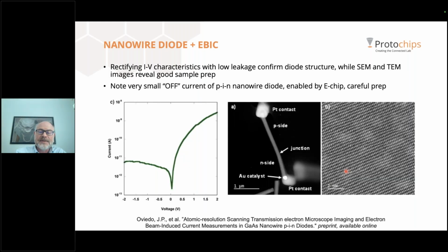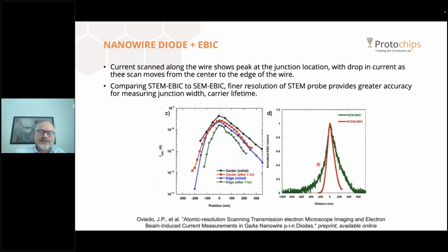So the first thing you want to do is measure the diode and confirm that it has diode behavior. You can see here on the left the classic rectifying characteristic of a diode with a very low off-state leakage current. You can see here it's sub-picoamp at low voltages with a nice rise in current when it's positively biased. And by looking at the sample in the STEM, you can also see that you've got good resolution on your images. The next step is characterization using EBIC.